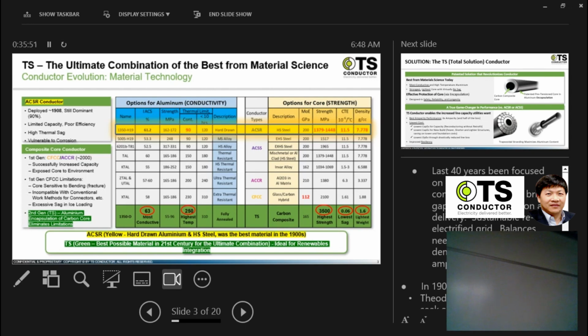Going back to the strength member side, to address the weight and also the thermal expansion, composite core was developed about 20 to 30 years ago to substitute for steel in terms of newer generation conductors. I'm going to talk about two types of them. One is called ACCR, which is a ceramic fiber, aluminum oxide, in an aluminum matrix. And this particular composite core, it did reduce thermal expansion of the thermal sag by half, and reduce the weight by about half as well. And that allows you to manage the what we call thermal sagging.